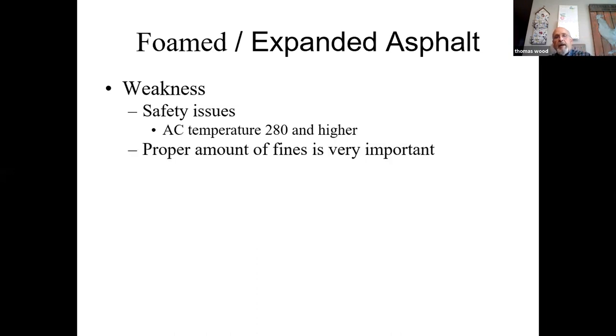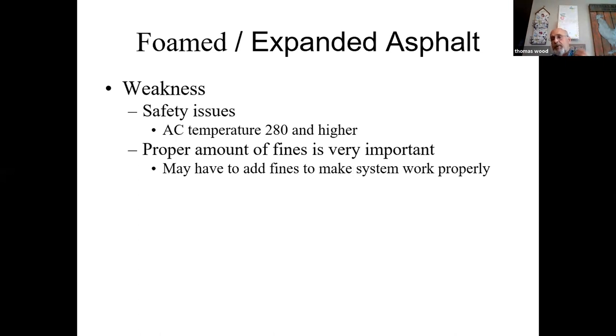Foamed asphalt, 280 and higher, needs to have the proper amount of fines in order to coat. If it doesn't have enough fines, it'll clump up. If you're doing a project and it's not working right, you may have to add some fines to make it work properly. The big issue, and over the time they've converted me, this used to be a huge issue to me, but now I've watched roads that have been recycled with foamed asphalt and they're performing fine. So it's not as big an issue as it used to be.